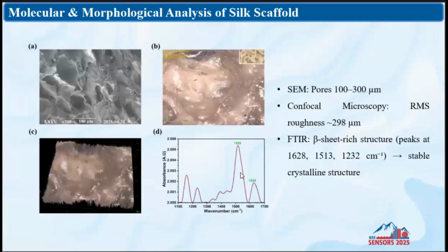And here is the characterization of the silk and porous silk. Initially, we did scanning electron microscopy to see the pore structure and surface morphology. Then we used confocal microscopy to see what the surface looks like, and the surface roughness. This surface roughness is also important to create more and more surface charge.